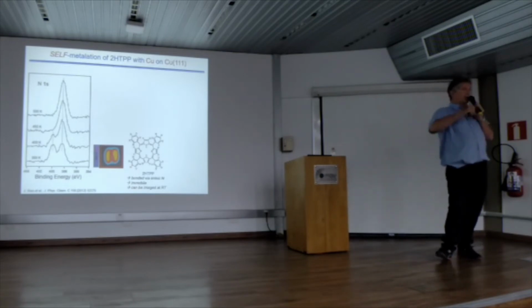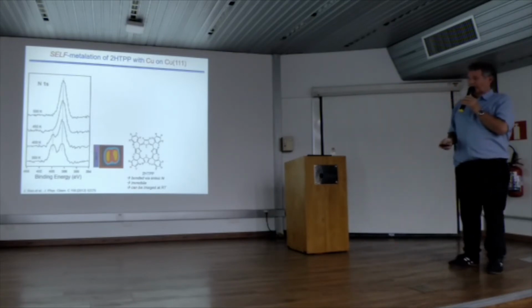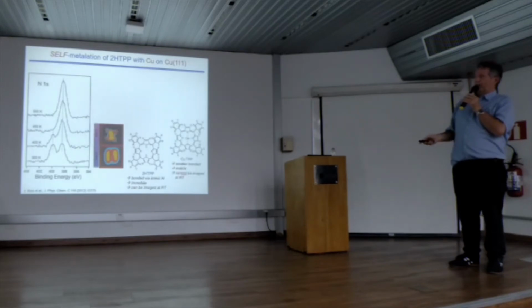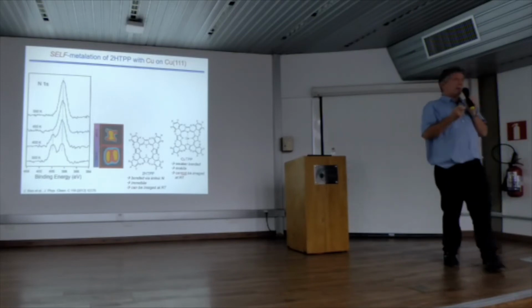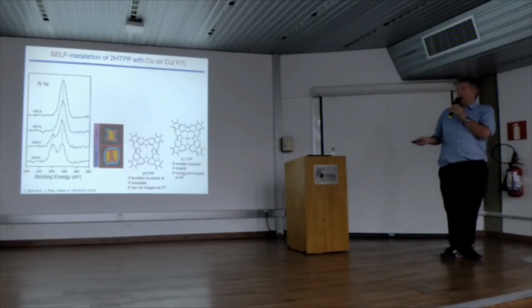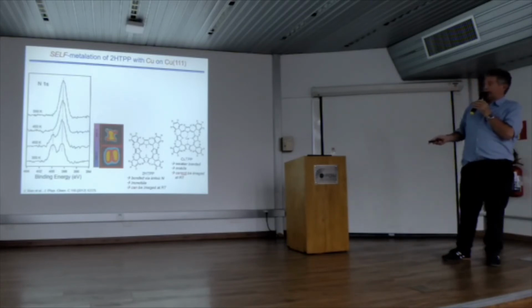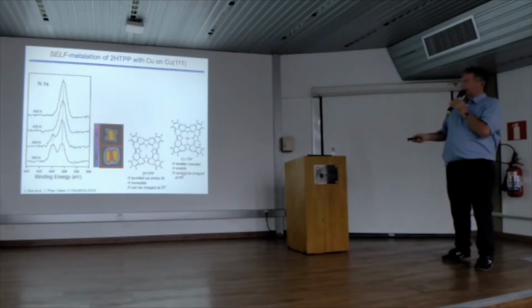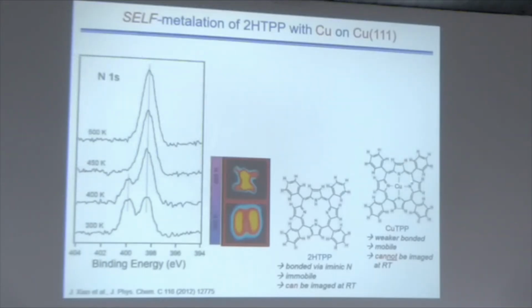You remember that these were the moving molecules, we could see them. If we have the copper porphyrin, you saw that on the surface where it was not interacting, the metalloporphyrin is inserted, and then all the nitrogens bind to this copper, and then the nitrogens don't interact with the substrate. So this molecule is extremely mobile and forms islands on the surface, so you cannot even image it at room temperature at low coverages. So you have to cool, and then you can see it. At room temperature, you don't see it. If it's cool, you see it, it looks completely different like that.